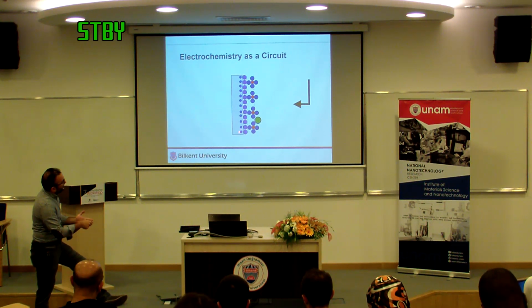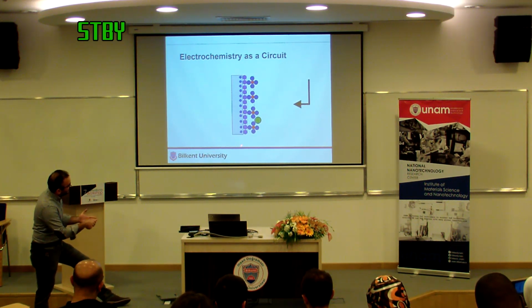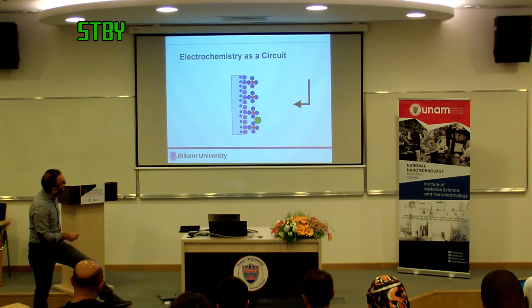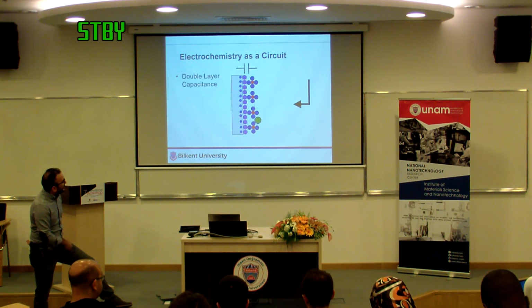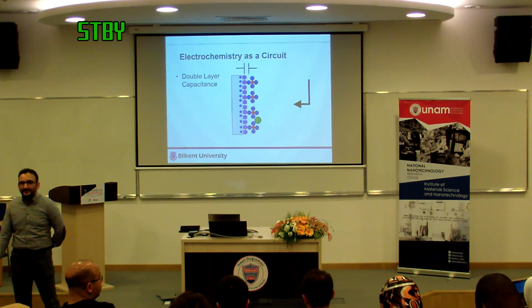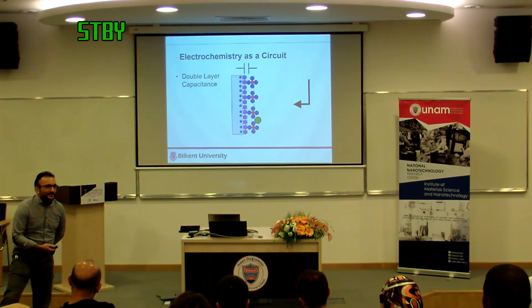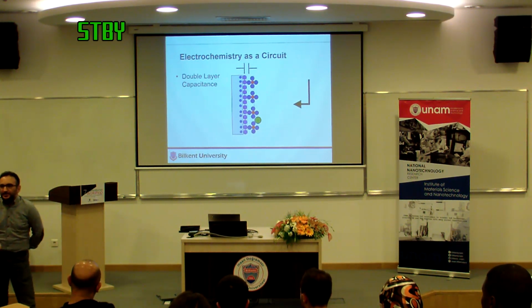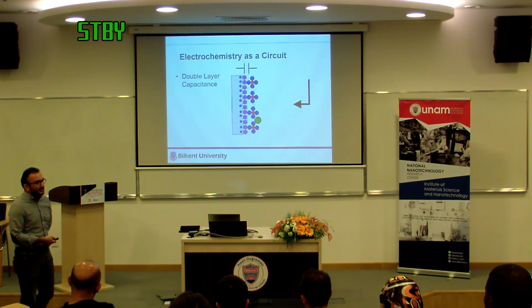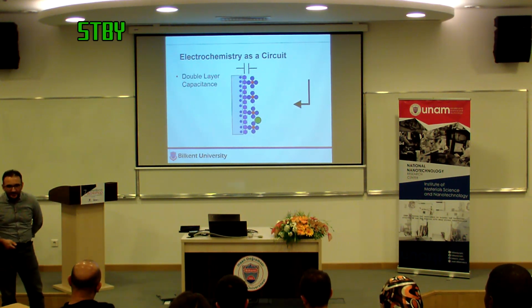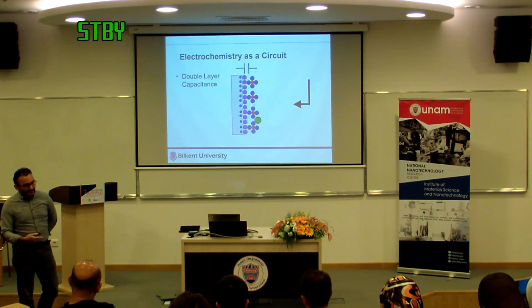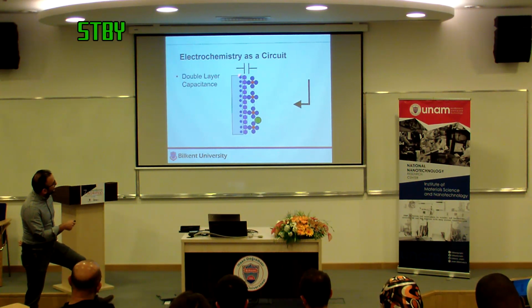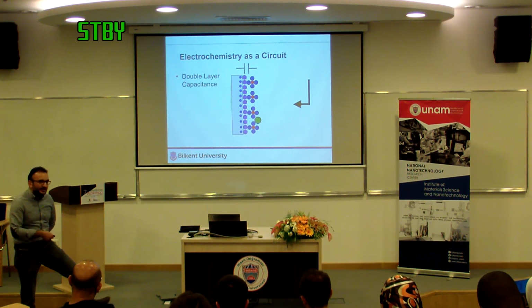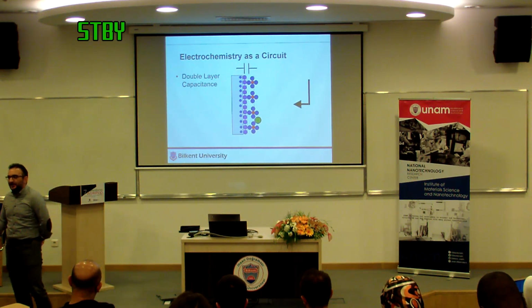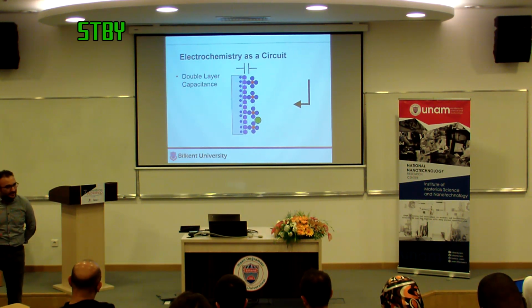So we have these charges on the electrode, charges from the electrolyte that sit right on the surface of the electrode. And this is what we call the electrochemical double layer. And in order to model that, a true parallel plate capacitor is something that is very logical to do because it looks exactly like a parallel plate capacitor. There is a big difference, and we're going to talk about this a little later, is the fact that there is no dielectric and this distance is very short. In typical electrolyte concentrations, 0.1 molar or above, this distance is less than a nanometer.